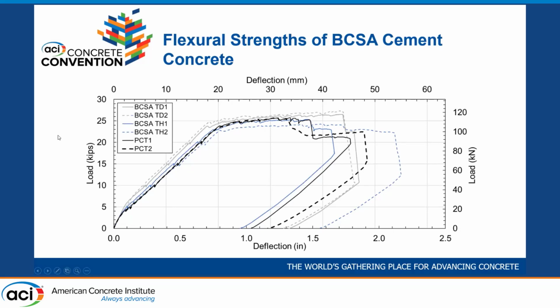And then if I plot the BCSA beams that were tested at 1 day of age on here, you can see they're a little bit stiffer, but basically they perform the same way. Similar cracking loads, similar yield point, similar load versus deflection failure after the yield. So that's all good.